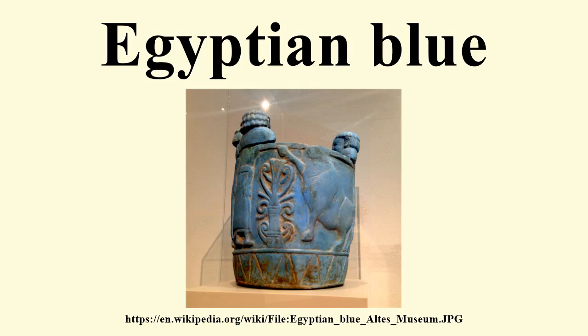This may have been intentional. An increase in the alkali content results in the pigment containing more unreacted quartz embedded in a glass matrix, which in turn results in a harder texture. Lowering the alkali content, though, does not allow glass to form, and the resultant Egyptian blue is softer, with a hardness of 1 to 2 Mohs.